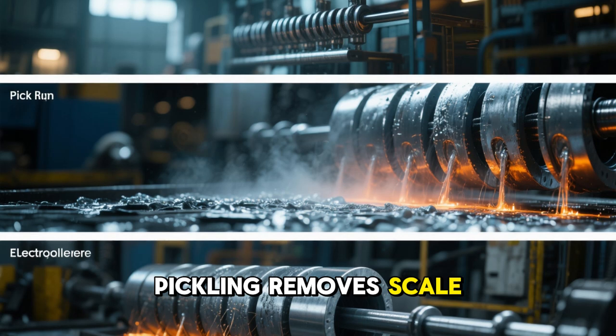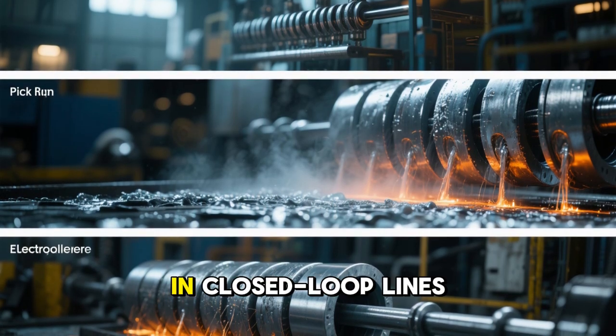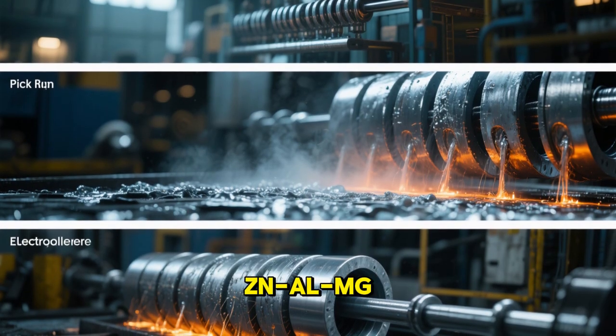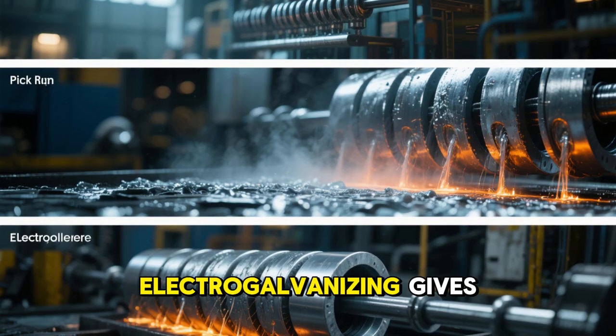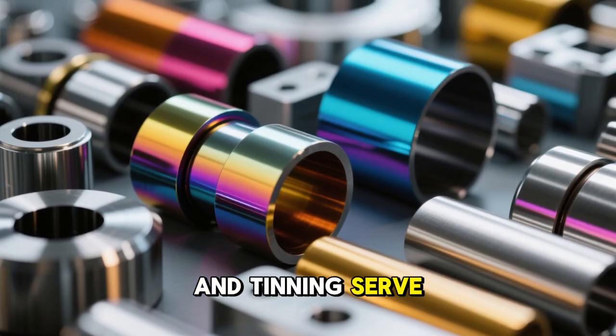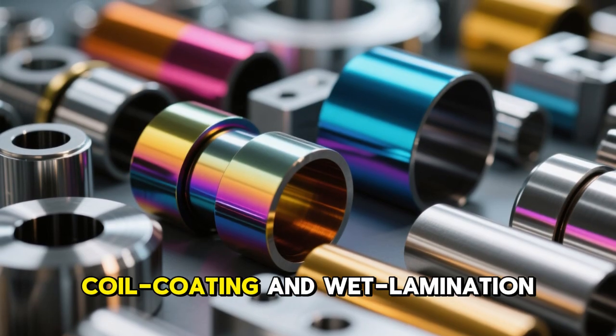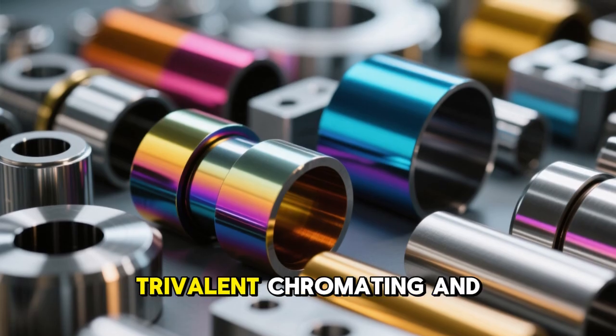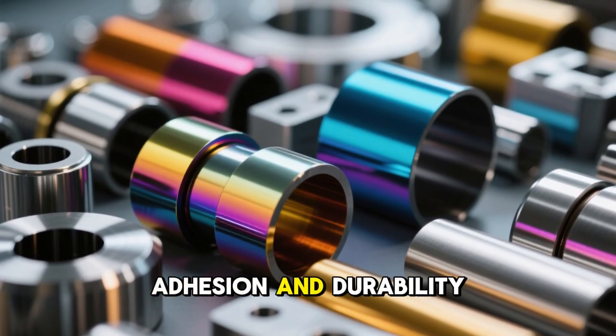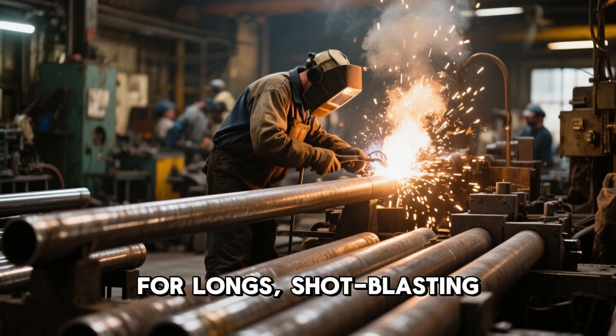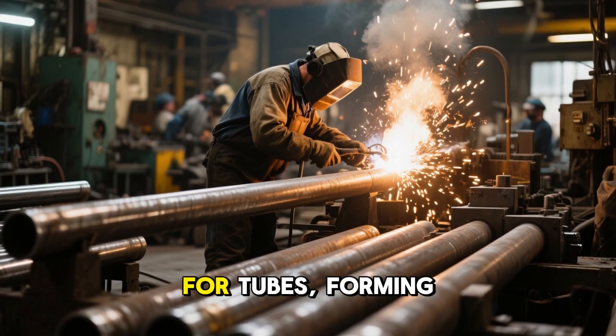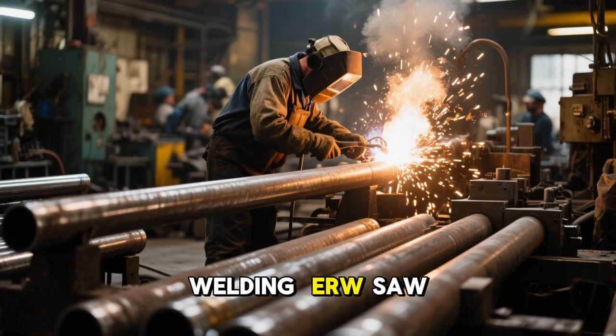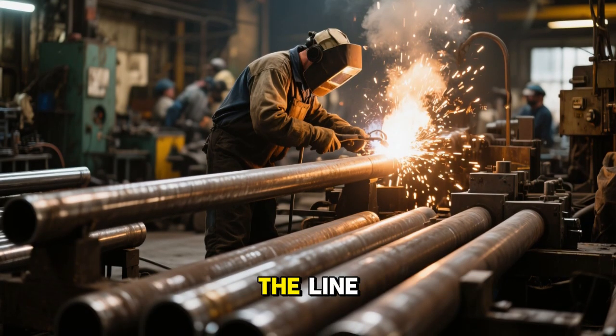Surface finishing prepares products for use or downstream steps. Pickling removes scale with acids, HCl, H2SO4, in closed-loop lines. Hot dip galvanizing, HDG, deposits Zn or Zn-Al-Mg coatings for corrosion resistance. Electrogalvanizing gives highly uniform thin coatings, aluminizing, AlSi, and tinning serve high-temperature or packaging uses. Coil coating and wet lamination produce pre-painted products. Trivalent chromating and sealers improve adhesion and durability. For longs, shot blasting and protective primers limit oxidation. For tubes, forming, welding, ERW, SAW, normalizing and hydro-testing complete the line.